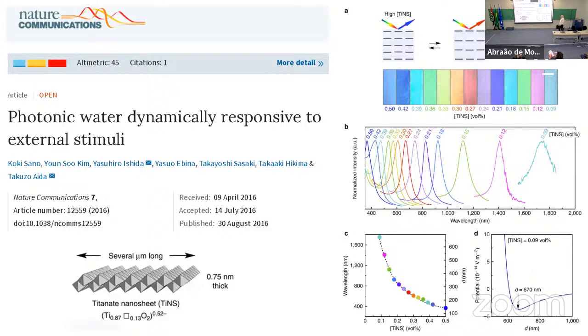So then we knew about this paper, titanate nanosheets in suspension. You control the distances between them by concentration in water. So this is called photonic water. Most of the material is water. There are some platelets with some distance, and you get colors back based on interference from layers in the depth here. So it's basically Bragg's law again.